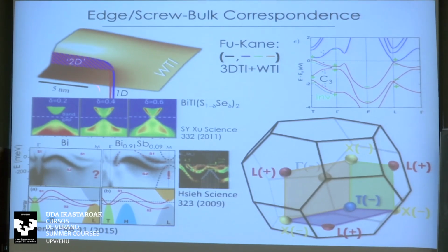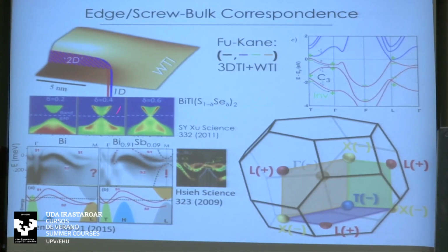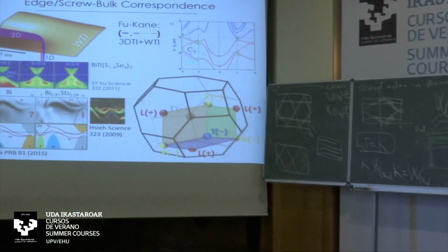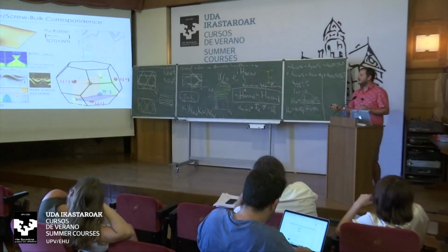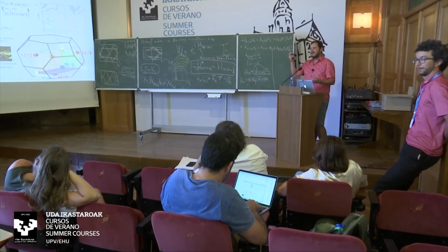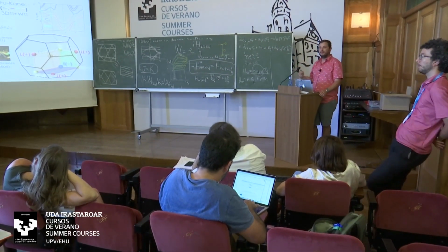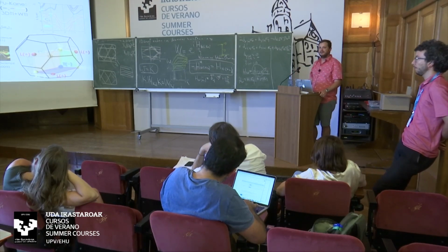what you see is not only the bulk gap closing gradually, but also surface bands which are practically helical start to be induced, pulled out from the bulk, increasing in intensity as the gap gradually closes. And this is approaching the critical region of the topological phase transition.